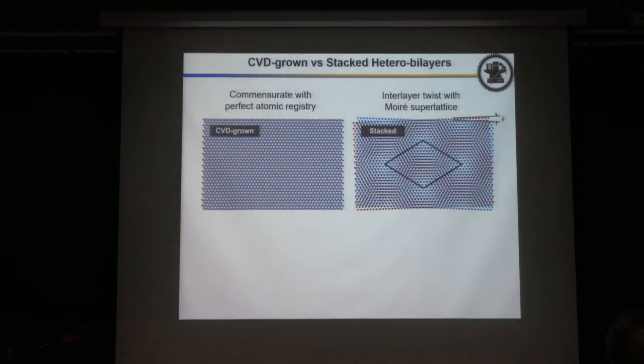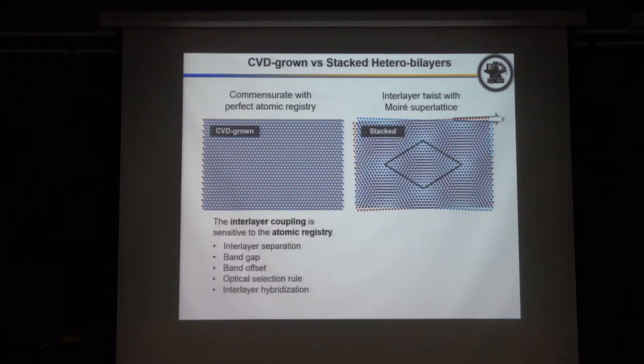And now if we stack two materials together, you have two different situations. One is so-called commensurate. Commensurate means that all atoms will stack perfectly with a very good atomic registry like this. And the other one is if we have some interlayer twist, or the two materials have a little bit of lattice mismatch, it will form this kind of Moiré pattern with periodic variation of the atomic registry. So we call this pattern a Moiré pattern or Moiré superlattice. This kind of commensurate vertical heterostructure, you can only use growth. You cannot use stacking to form this kind of structure.